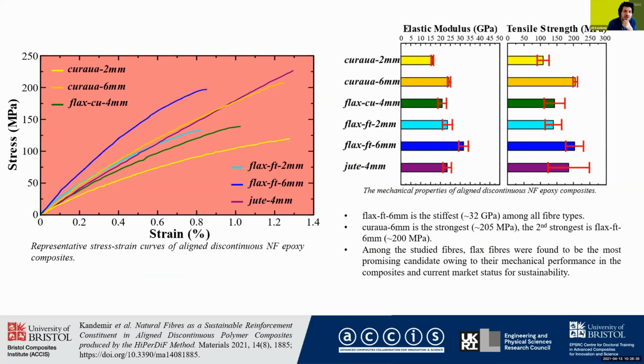It's seen that 4 mm jute composites, 6 mm curaua composites, and 6 mm flax fiber epoxy composites showed promising overall mechanical performance. However, we found that only 6 mm short flax fibers are the best candidate due to the high stiffness, strength, also due to their current market status, availability, especially for the UK market, that hints its potential for sustainability. The study includes these results and also results with polypropylene and PLA polymer composites, recently accepted and published in a special issue of Materials, which is open access and people who are interested can easily check.